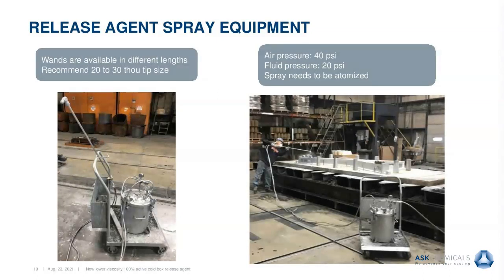Several manufacturers supply release agent equipment. Release agents are typically sprayed. Depending on the application, wands are available in different lengths, typically from 1 foot to 6 feet. Tips are available in a fan or conical configuration. Which type is used depends on a variety of factors, including whether the material is being manually or automatically sprayed, how deep the pattern is, and how much room there is, i.e., how thin is the section. It's important that the spray is atomized as opposed to droplets, which will create stickers. A good starting point for air pressure is 40 psi and 20 psi for fluid pressure. Normally, the fluid pressure is half the air pressure.